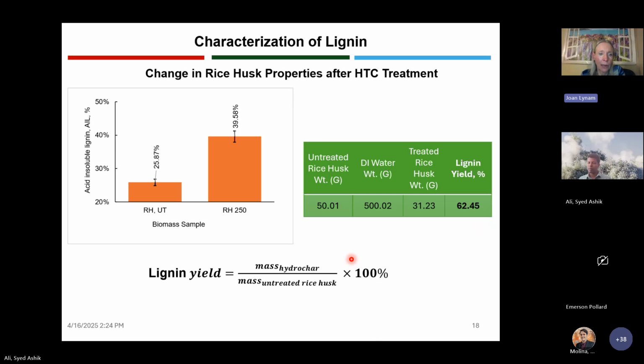And you can see that the acid insoluble lignin went up in the rice husk, and we had a lignin yield of about 60%. So that's what happened when we did hydrothermal carbonization on it. And we can go on to the next one.